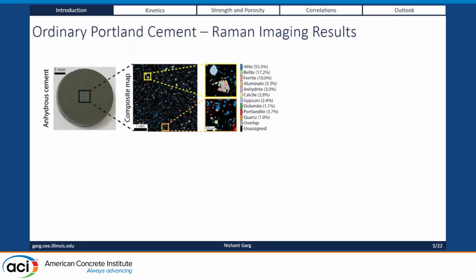We get this very high resolution Raman image. We can quantify most of the phases. Each of these images that you're looking at has 250,000 pixels in it. So it's a really high resolution image at a large area, 5 millimeters by 5 millimeters, which gives us statistics that it can then correlate with the bulk XRD measurements. We did this on a variety of 11 different cements from the US. We get a decent correlation.